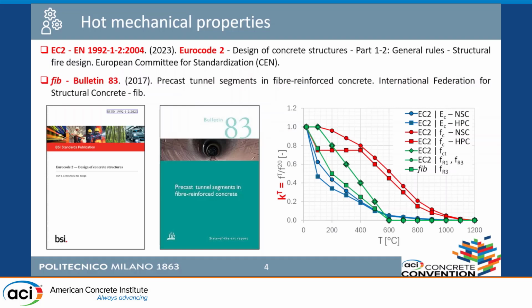While in the FIB Bulletin 83, this is the only curve that refers to these guidelines, in which the tests were performed directly aiming fiber-reinforced concrete, we see that this curve is more conservative than this one. So it is interesting to understand if the suggestion given by the EC2 can be more or less appropriate than what the FIB bulletin does.